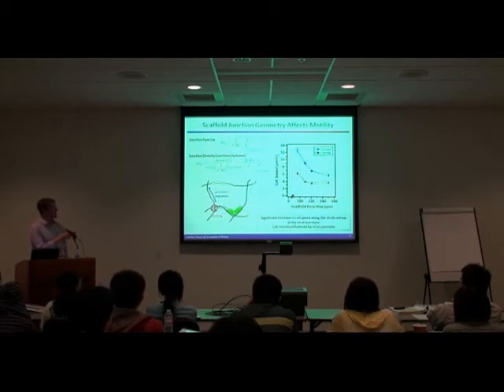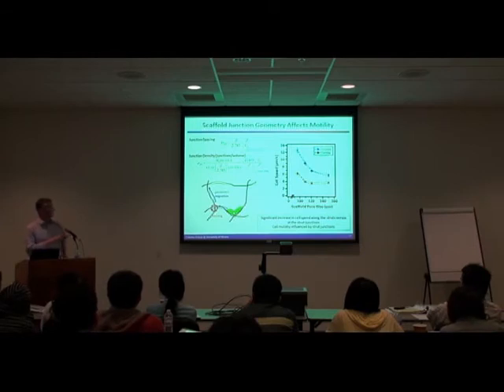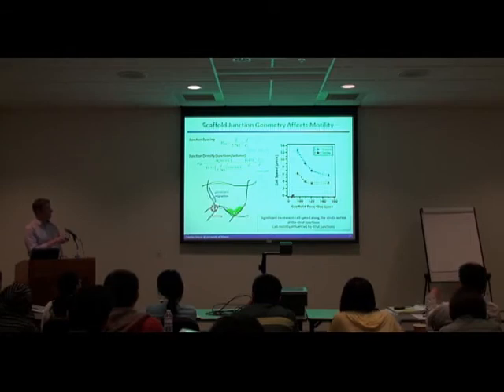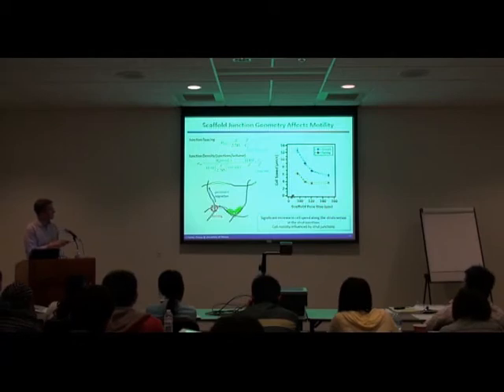if you really wanted to get a sense of how does the spacing between junction points change as pore size changes, or what's the overall density of junction points within a biomaterial. Again, it relates to the average diameter of the scaffold, or inversely proportional to the average diameter cubed of the scaffold, depending on whether it's the spacing or the density.